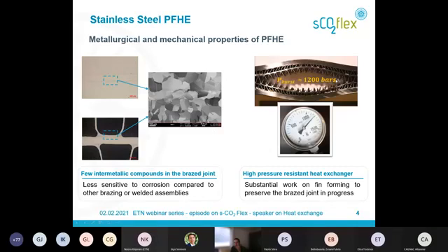We succeeded to reach pressure rupture of 1,200 bars. That was not an evidence at the beginning of this project, because we were not able to reach 800 bars at the beginning. So we made substantial work to be high mechanical resistance, and we're still working on that, especially on fin forming, to go on higher pressure of rupture.